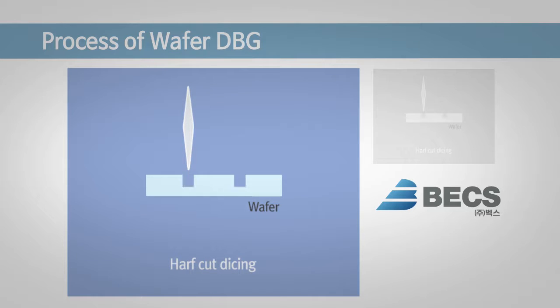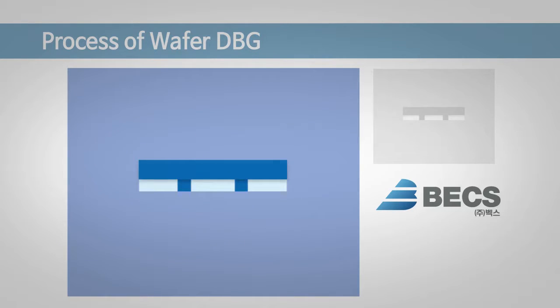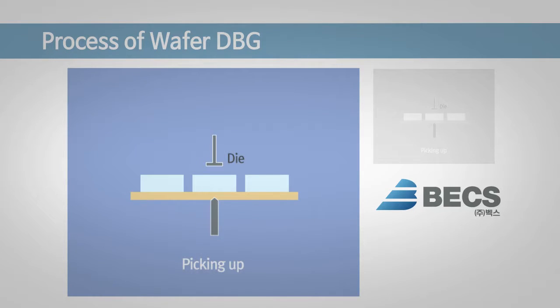The back grinding coating agent liquid type of Bex is especially simplified in the manufacturing process. The process is cut down from the existing seven steps — wafer loading to de-taping — to four steps: wafer loading, molding, back grinding, and de-taping, using the mold system of Bex.